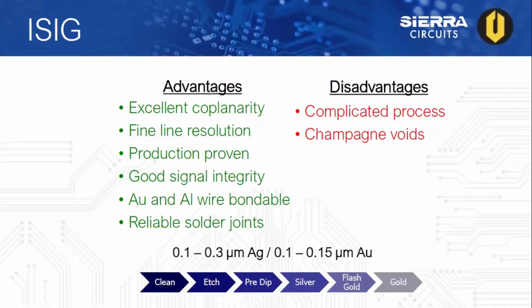Now the process sequence is going from starting at the cleaner, etching the copper, going into a nitric based pre-dip, plating with silver immersion, applying a flash gold, and then also finishing off with a thicker gold deposit.